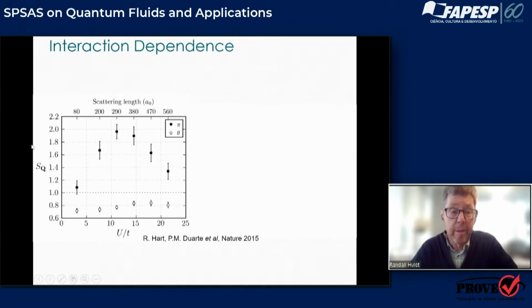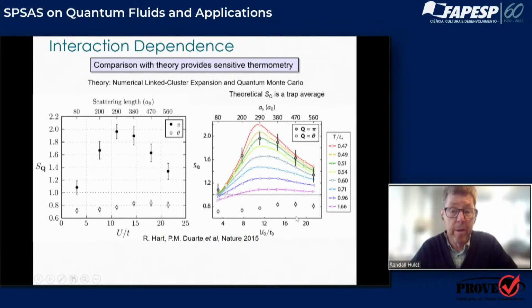So this is in fact what we saw. This is the absolute magnitude of that spin structure factor versus interaction strength U over t. So this in fact looks a lot like Therese's calculation with quantum Monte Carlo, in that there's this nice maximum at around U over t of about 11 or 12, something like that. And so that actually matches the theory pretty well. It's shown here for the different colored lines, the theory lines corresponding to different temperatures. And if you look closely at the data, you can see that it matches the dark green temperature the best, a temperature of about 0.5 in units of the hopping. And the fit is really, I think, remarkable, that it fits almost exactly on this line.